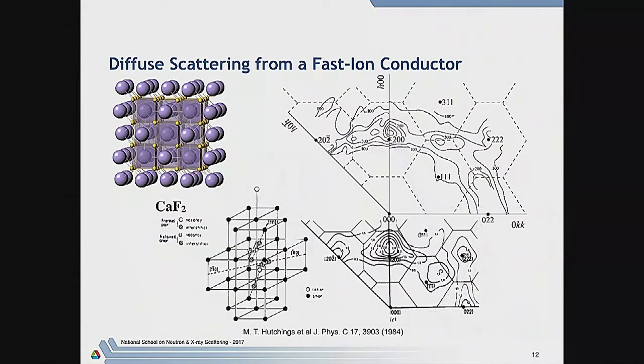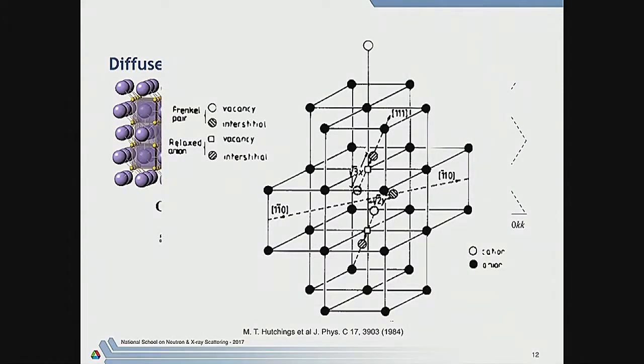And we're able to model that in terms of a very simple structure, which consists of... So here the anions sit on this simple cubic lattice, the black dots. So the idea is that if you have mobile anions, some of them are going to move into this empty cube center. Here's the striped one here. This is the Frenkel defect that's created when these anions become mobile. And it moves into this empty cube center, and the neighboring anions here and here relax. Okay, and just that very simple model allowed them to reproduce most of the diffuse scattering.